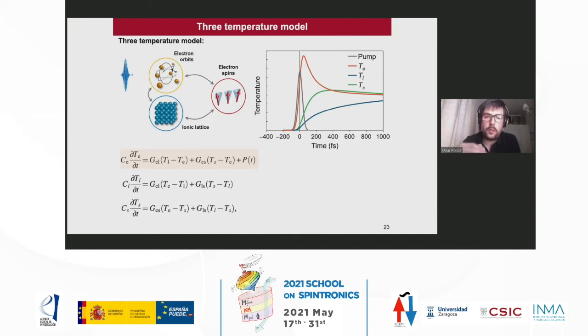This is like a Gaussian profile. The electrons absorb this energy, and if you look at this orange curve, the electron temperature increases. Then in the second equation, which corresponds to the lattice, since they are coupled via electron-phonon coupling, the electrons transfer energy to the lattice, and the lattice starts to heat up, increasing its temperature, and the same happens to the spins.